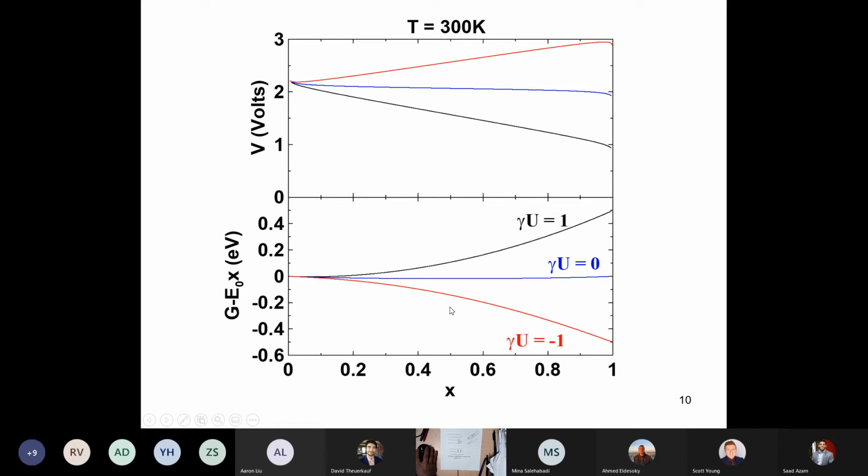Well, then the free energy of the material at 50% full would be made up of the average of the free energy of the empty and full. It lies along the straight line between the endpoints, and it's lower than the free energy of the random mixture. So I'll show you what I mean.